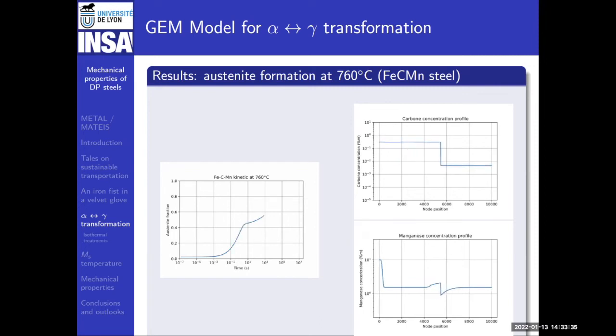What is the triggering reason that at some point it starts there? Is there something specific? No, in fact, the trick is the log scale. If we advance more and more on the log scale, then manganese at the end has time to diffuse. The whole thing is the characteristic time for manganese to diffuse. Here, there is no time for manganese to diffuse, but in this domain, manganese has time to diffuse. And that's why you see the interface. It was there, but you could not see it looking at this graph.